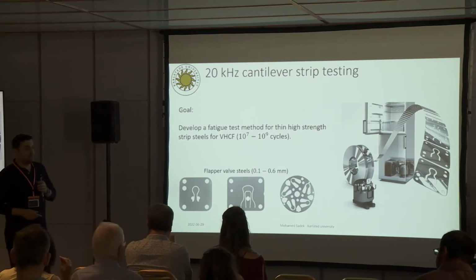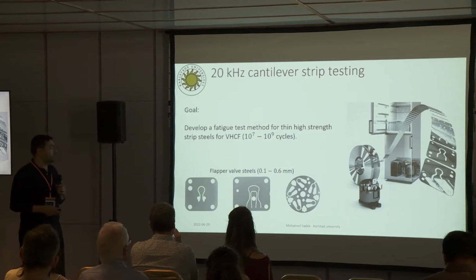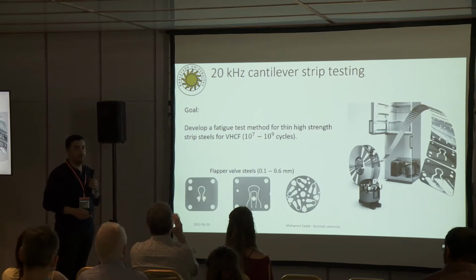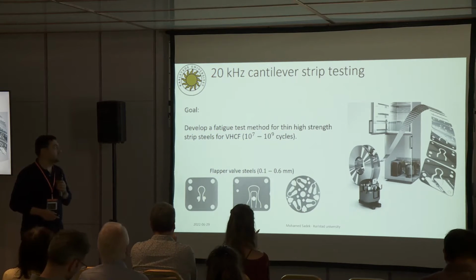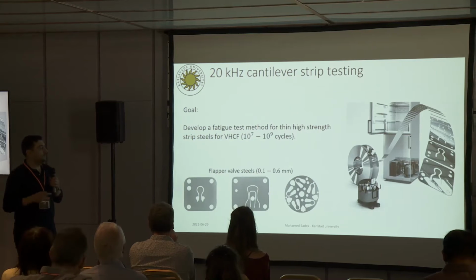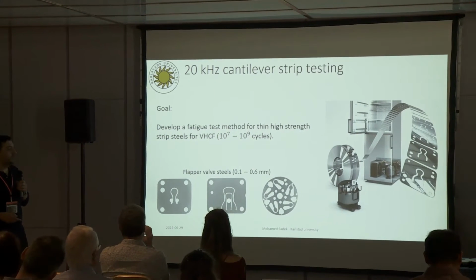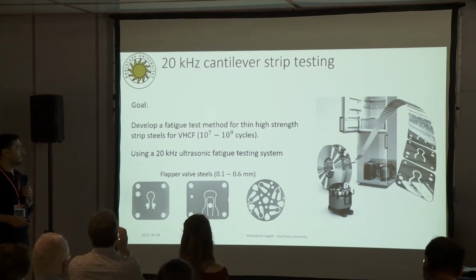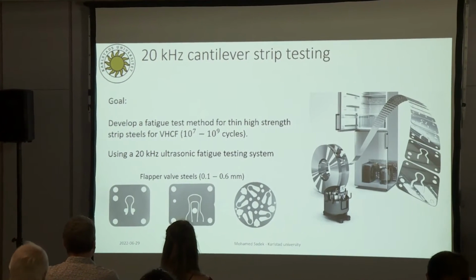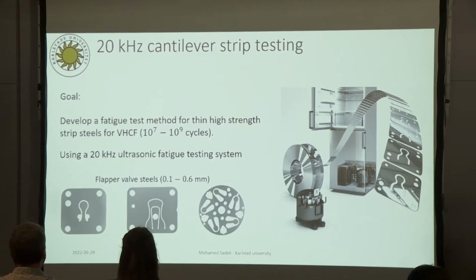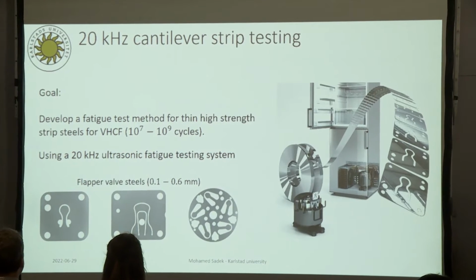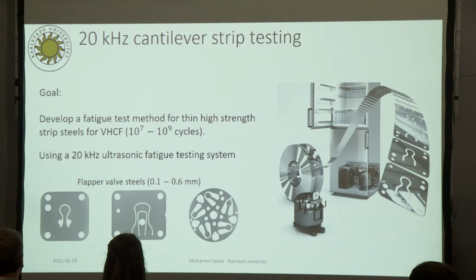So the goal of this work is to develop a fatigue test method for thin, high-strength strip steels at 20 kHz for very high cycle fatigue in the gigacycle regime. To do that, it's best to use the ultrasonic fatigue testing system. Then we can reach these lifetimes within reasonable times.